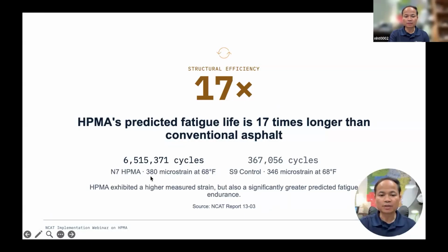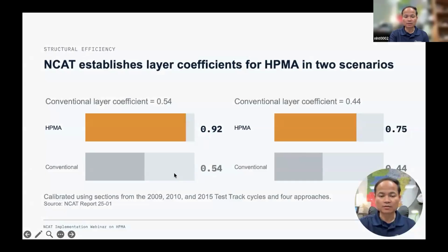You can see here the number that the strain gauge placed at the bottom of the AC layer for N7 measured at 380 microstrain, and the S9 here at 346 microstrain. And then we took that microstrain, put it in the bending beam fatigue test result, and here's the number of cycles that last, as predicted based on that. You can see here 17 times greater. Even though N7 carries higher microstrain at the bottom of the AC layer, it still lasts longer.